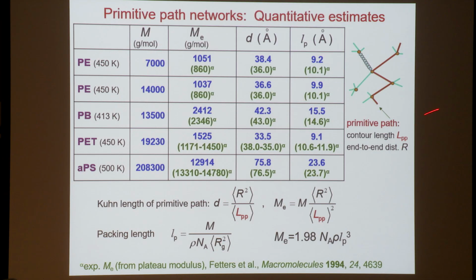From the mean length of the primitive path, one can calculate this quantity here, the Kuhn length of the primitive path, or the entanglement tube diameter, and also this ME, which is the molecular weight between entanglements. So here we see characteristic values for 4 polymers: polyethylene of 2 different molecular weights, polybutadiene, polyethylene terephthalate, atactic polystyrene. We have the ME values and the entanglement tube diameter values, and they are being compared, the blue symbols are from the topological analysis, against estimates from rheological properties by Lou Fetters, and by and large you can see that the agreement is not bad.